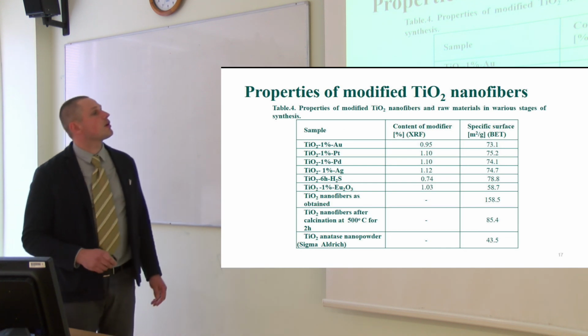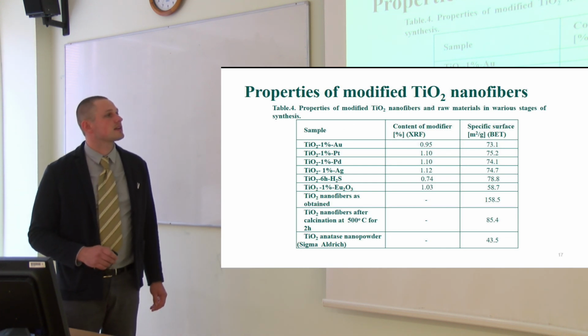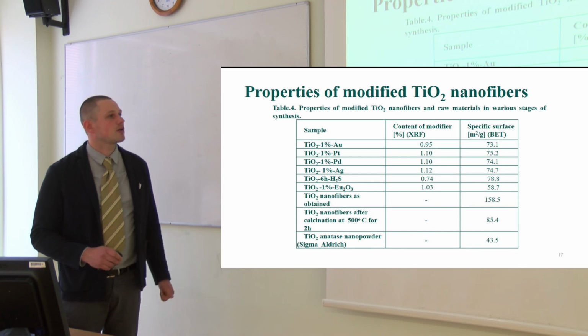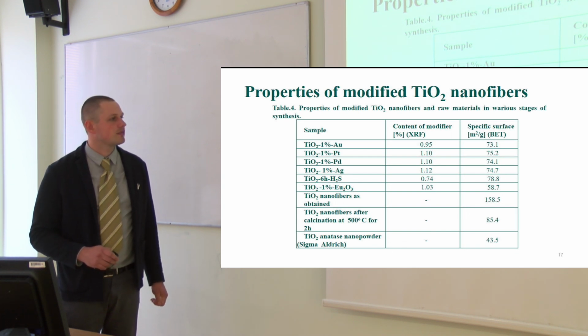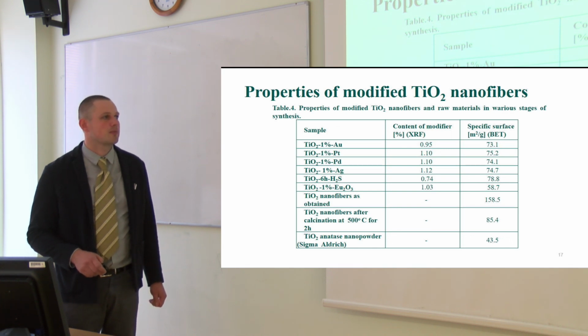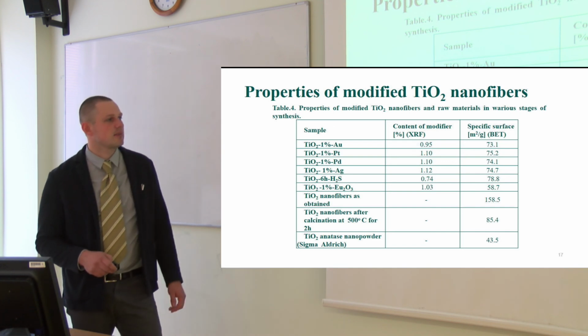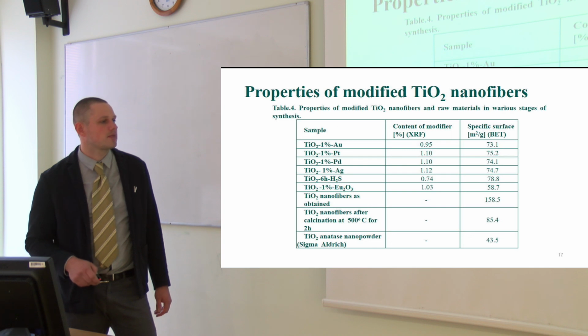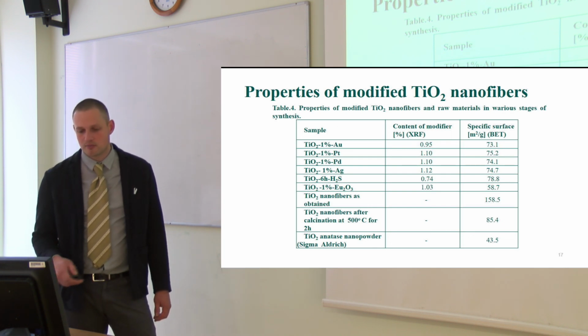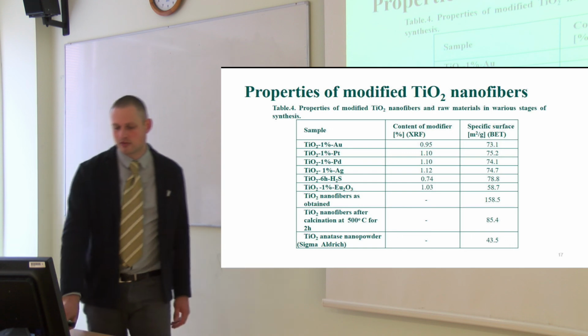So here is a summary of properties of titanium dioxide nanofibers modified with various modificators. As you can see, after synthesis, pure titanium dioxide nanofibers are with extremely high specific surface area, but after calcination, after modification with modificators, this surface area decreases, but still we have almost 2 times bigger surface area than our raw material titanium dioxide nanopowder.